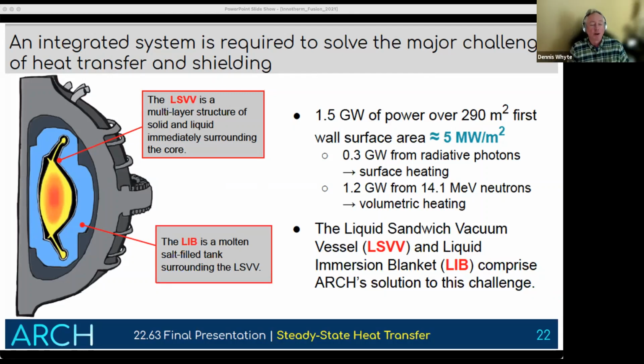How sensitive is the entire ARC system to impurities in the FLiBe salts? Do you expect you will need to continuously filter the salts or reload with fresh salts? Yeah, so it's a good question. The overall performance of the salt is not greatly impacted by impurities. In fact, the salt is a lifetime component essentially in ARC, because the relative amount of depletion of the materials in it is so small, you can keep it in there.